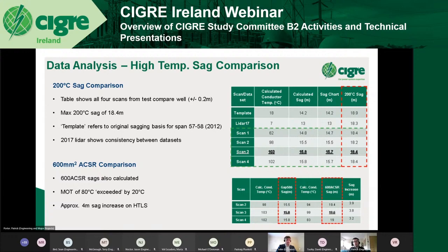But more importantly, and I think this highlights the benefit of the gap conductor pretty well, you're looking at an almost 4 meter SAG increase at maximum operating temperature. So that really highlights the benefit of the non-conventional conductor versus the conventional conductor when you're operating at these higher temperatures. If you think back to one of the earlier slides where I said no significant compromise in clearances, that's essentially what the gap conductor is giving you.